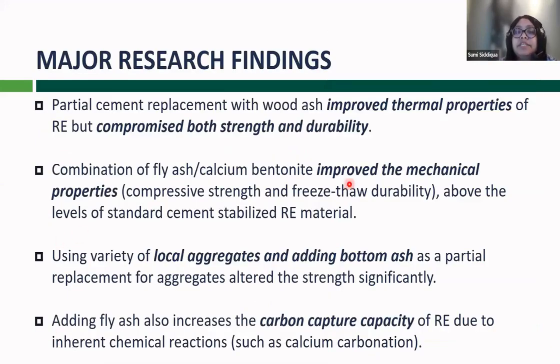So with this, the major research findings from this rammed earth project were: we have been able to replace partial cement with wood ash, improving the thermal properties of the rammed earth, but we compromise the strength and durability. Combination of fly ash and calcium bentonite improves the mechanical properties, that means compressive strength and freeze-thaw durability, above the levels of the standard cement stabilized rammed earth material. Using a variety of local aggregates and adding bottom ash as a partial replacement for aggregates altered the strength significantly. And we also saw that adding fly ash increases the carbon capture capacity of rammed earth due to inherent chemical reactions such as calcium carbonation. So these are the findings from the rammed earth.